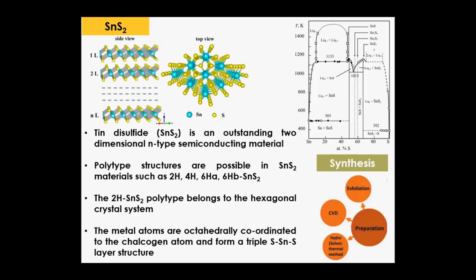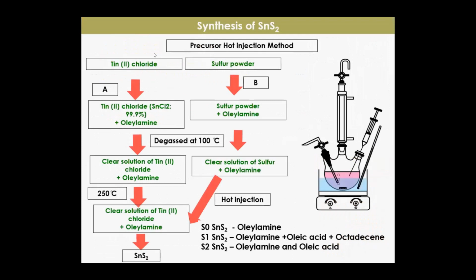To maintain a single phase, we wanted to choose a particular synthesis method and control the sulfur and tin segregation. We can also avoid tin trisulfide, Sn2S3, these kinds of excess combinations. So I chose the precursor hot injection method. In this method, the precursors are dissolved in high boiling point solvents like oleylamine, oleic acid, and octadecene. The boiling point of these solvents is nearly 310 degrees centigrade. So we chose all three solvents for this investigation.